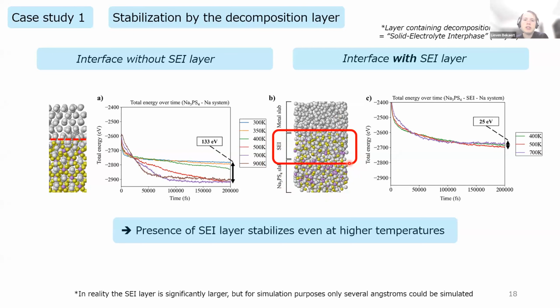And then we ran the simulations again, and you can see that at different temperatures, in the absence of this SEI, there is quite an energy difference between the different temperatures, showing that at higher temperatures there was a significant decomposition or reaction between these two materials. But if you have the SEI material in between, then you have a very small decrease in energy, which really shows that having this layer really stabilizes the interface. So it shows that it's a good decomposition layer. Now, in reality, the SEI layer is significantly larger, in the nanoscale range, but for simulation purposes, only several angstroms were considered in this study.